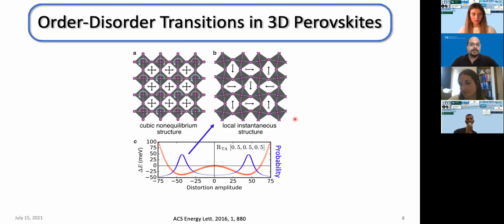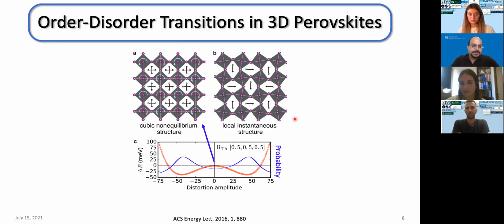As we increase temperature, we populate more and more vibrations, the amplitudes of the motions increase, and the atoms start sampling more and more of this double well potential, until at some point, there's a possibility to cross the barrier of the double well potential. The atoms sample all of the double well potential. Now, in this case, the dynamics is still governed by the bottoms of the well, as you see by these probability curves here. But the structure, the one that we measure in XRD, which is the average structure of all of the configurations of all these octahedral rotations, is the untilted one, the one at 0 octahedral tilt, giving us a higher symmetry, in this case, cubic phase.